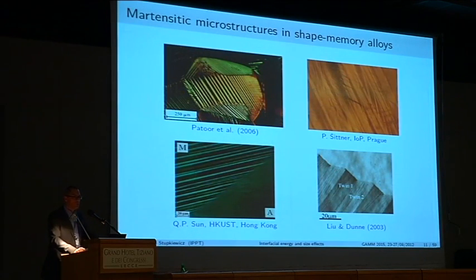Okay. So if we take a magnifying glass and look at the material, which undergoes this martensitic phase transformation, what we see are microstructures. And the microstructures, martensitic microstructures, are at the very essence of these materials. So here you see some examples of the microstructures. On top left you see a grain in a polycrystalline material with stress-induced martensitic plates. So you have the whole grain which transforms into some zones. In each zone in particular you see laminates of martensitic plates and the parent austenitic phase.